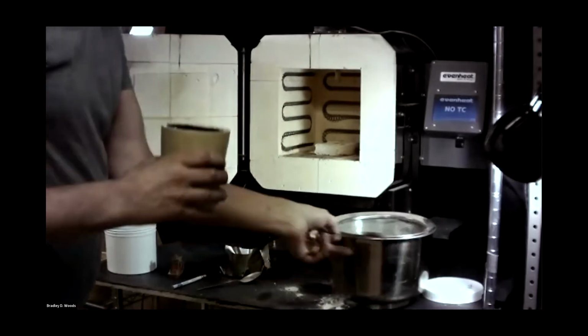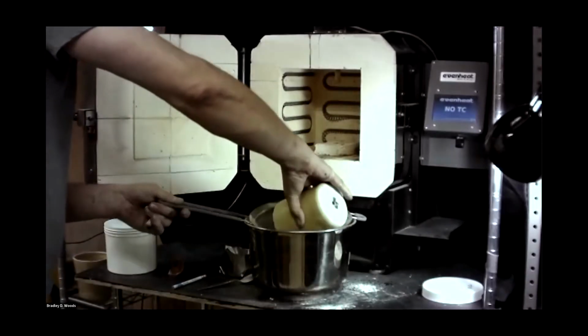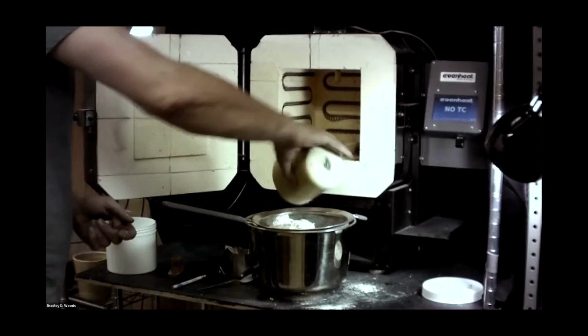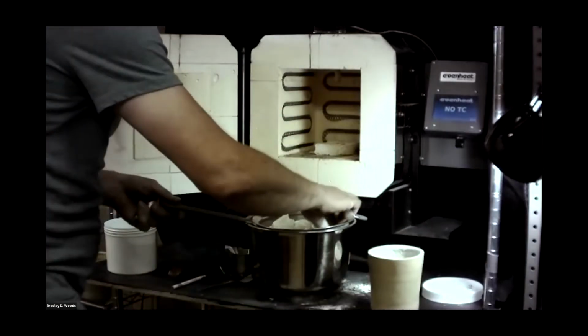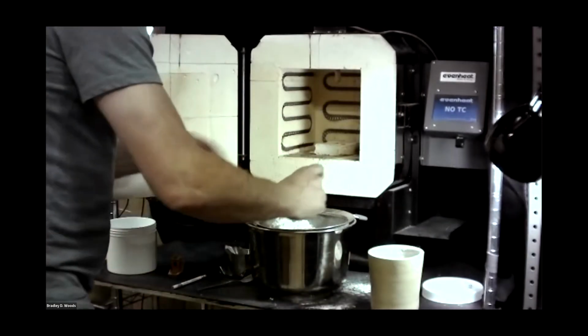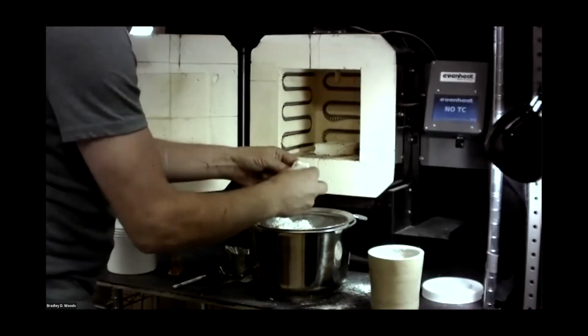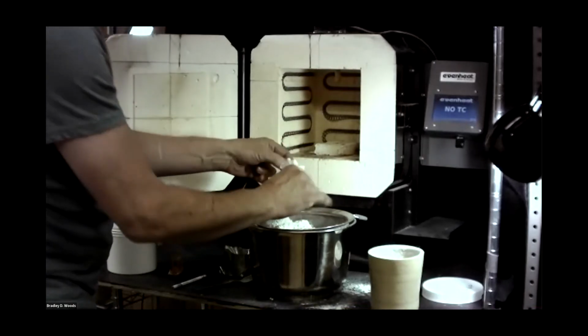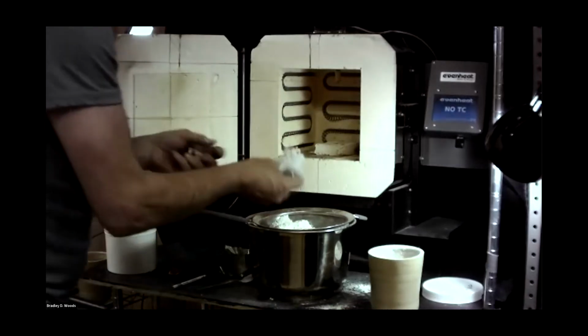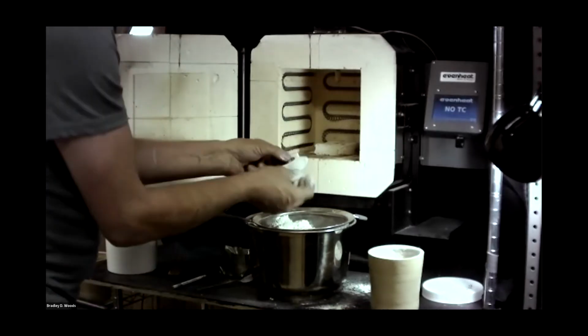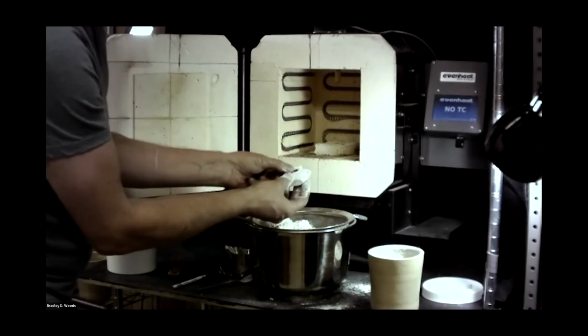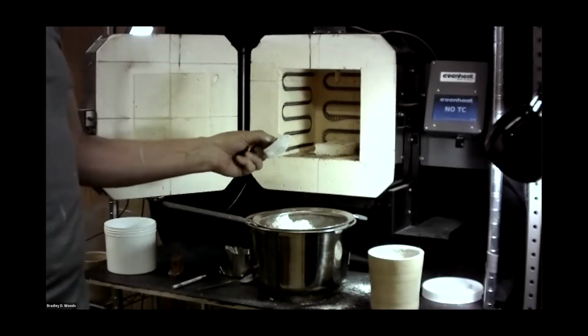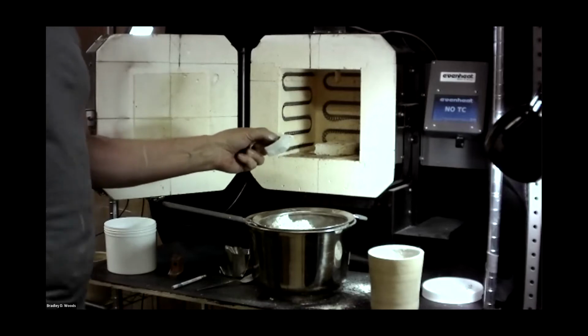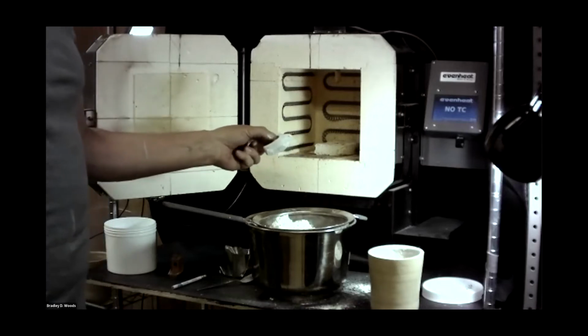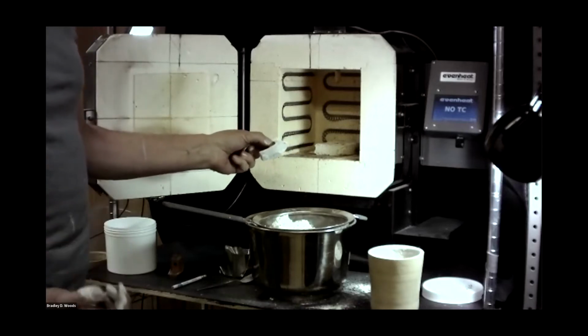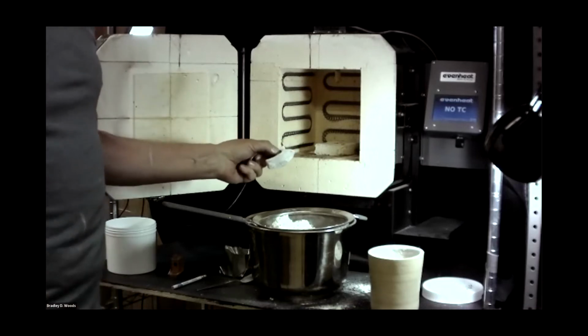We'll take the crucible out. In the same way, just dump it into a sieve so we can find our part and fish out your brown part, or your sintered part. And it'll pretty much look like this. Brad, how do you know that your sintering carbon was used up? What does it look like at the end? If it's there, it wasn't used. If it's black, sometimes it'll get a little bit of yellowing to it, but pretty much as it's consumed, it becomes a gas. So it's just gone.